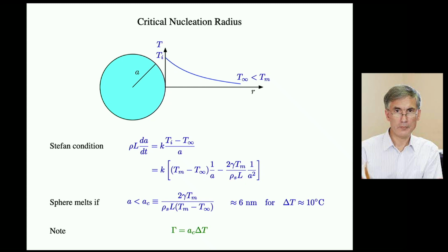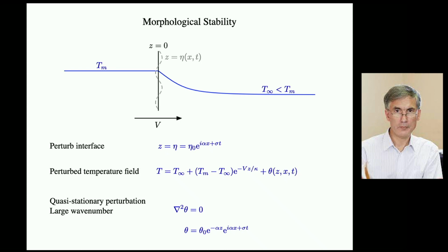It happened because, as we'll see mathematically, if we are solidifying into a supercooled melt, which is what we were doing, then the interface between a solid and a liquid, if we assume that the interface is planar, and then perturb it a little bit, we find that the interface is unstable to perturbations. Okay, it cannot remain planar. So we can't grow a nice ice cube to put in our gin and tonics by supercooling the liquid first. We have to do that by cooling from a boundary.